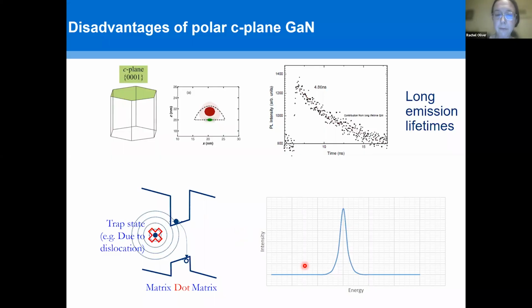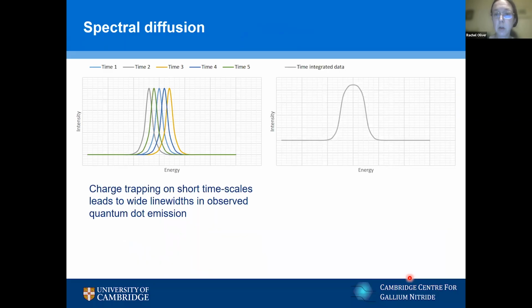So if we can have many different traps around my quantum dot, and they're sometimes charged and sometimes uncharged, and the charges hop on and off them, then instantaneously we might have a quantum dot emission like this, just as a sketch. A few nanoseconds later, perhaps, we'll have a different wavelength for the emission, and then another different wavelength as the charge environment changes and fluctuates. All these different wavelengths will then sum up to the emission we see, which will be a much wider peak than we might ideally expect from a quantum dot. So we see this charge trapping phenomenon in wide line widths in the quantum dot emission.